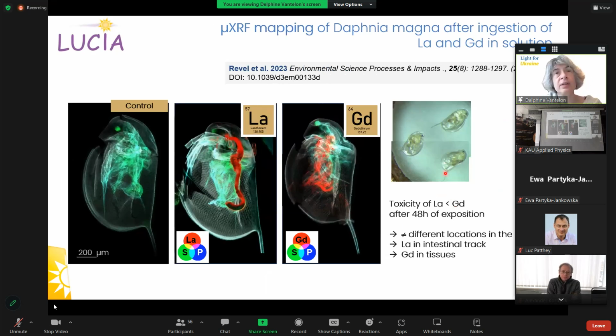Here is an additional study on the effect of ingestion of rare earths and the toxicity on daphnia, because here, as you can see, we could study the whole specimen, that it is small enough, and with sulfur you follow the organs of this daphnia, and here you have the location of the lanthanum in the intestinal tract. And here you have the distribution of the gadolinium, which is now in the tissues. And the users observed that the gadolinium was more toxic than the lanthanum. And here we could observe that it is localized in the organs of the species, in the tissues.